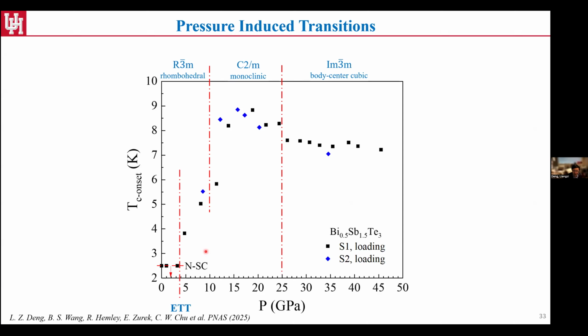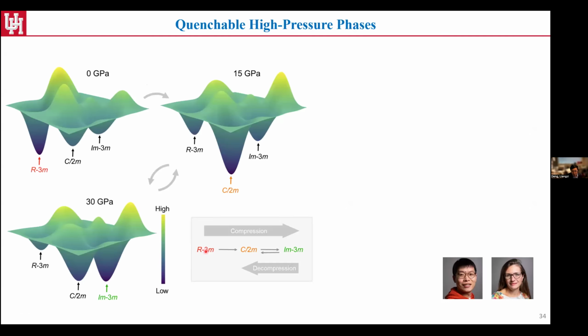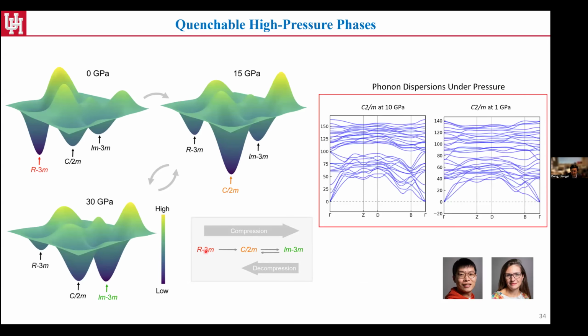So the next step, this is really just finishing our first step of the PQP. The next step is to do a pressure quench. So again, we talked to Eva, asking from the calculation point of view whether this high pressure phase is really quenchable. They were nice enough to look into the details and do some phonon dispersion calculations. A lot of work has been done, and eventually they pointed out, which is really interesting, that when we drive this phase above 10 GPa to form the monoclinic phase and then relax the pressure, from the calculation point of view it should be able to exist even at 1 GPa, right?